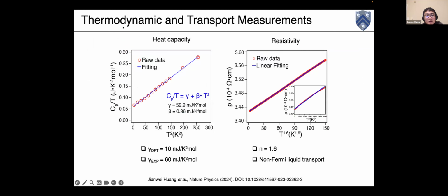And then our collaborator also did heat capacity and resistivity measurements. They show that there's a very large Sommerfeld coefficient, which presumably comes from the flat band at the Fermi level, and also this non-Fermi liquid behavior from the resistivity measurement that shows the effect of the flat band.